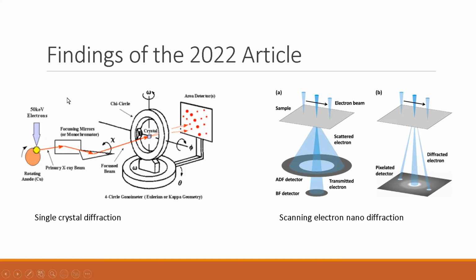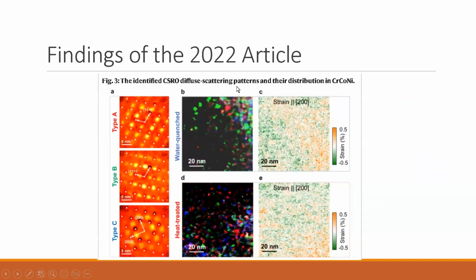So normally, single crystal diffraction is used for analyzing these superalloys and their crystal structure. However, this becomes problematic for examining medium and high entropy alloys because of the complexity of the alloy mixture. So the study used scanning electron nanodiffraction, which does a better job on that. And as we can see, they have discovered 3 types of nanoclustering and chemical short range ordering, types A, B, and C. And they used water quenched and heat treated, so 2 different samples. And they have seen that in the chemical short range ordering, there's an order. It's not totally random the way these elements are distributed in the FCC structure.